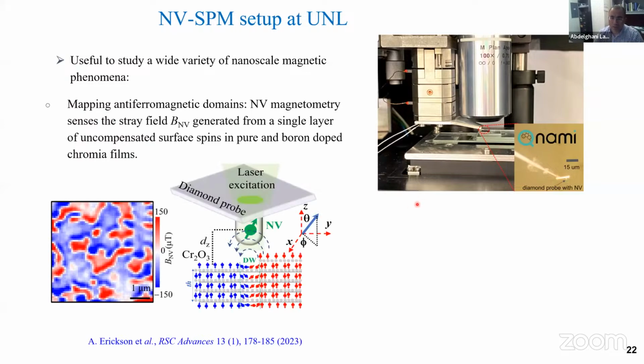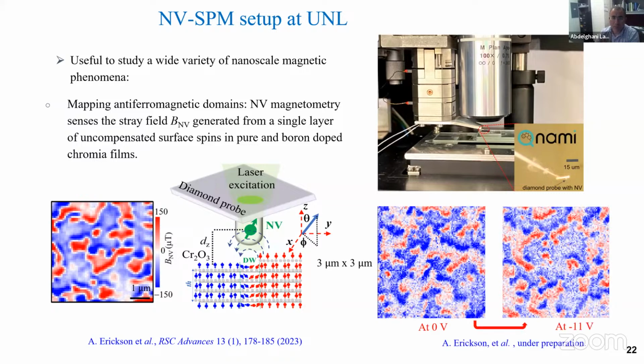In my lab, we use this particular NV SPM to study antiferromagnetic domains. In this case, we collaborate with Professor Binek. We study these antiferromagnetic domains in boron-doped chromia, because of the uncompensated surface spins, one can measure very nice domains. If you do MFM, you see nothing. That shows how NV SPM is very useful to study these antiferromagnetic materials. Recently, we can also switch magnetic domains at zero applied magnetic field in these boron-doped films. We are working on this for another paper.